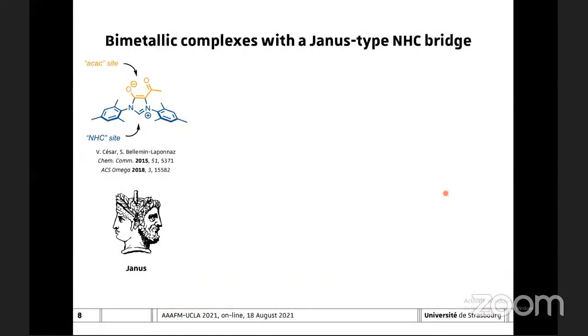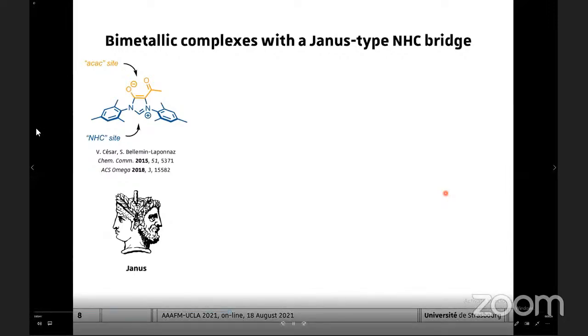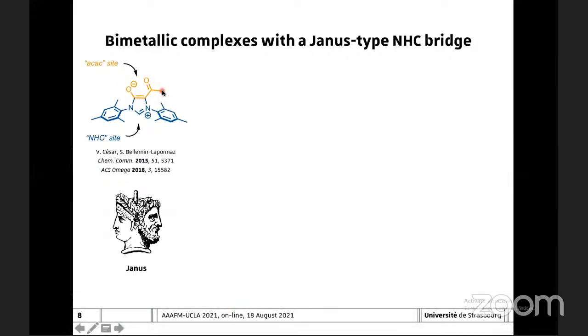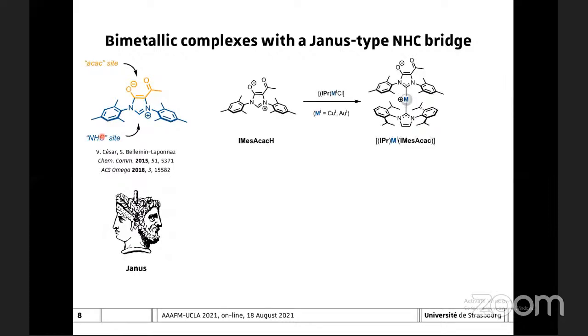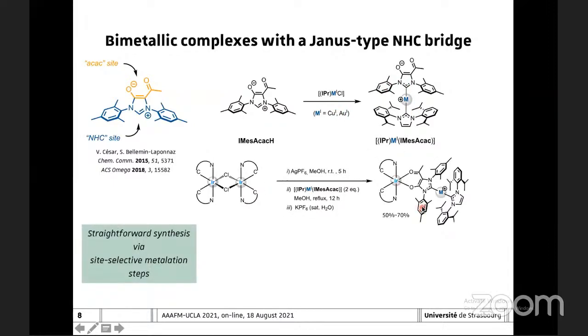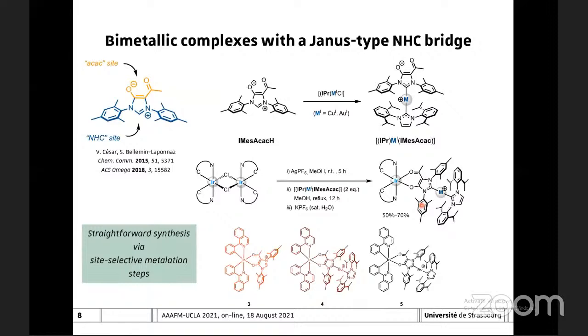So we then came across an interesting ligand. It is a Janus type ligand which possesses two different coordination sites. On one hand, the acetylacetonate site, which is very useful for the preparation of luminescent complexes, and on the other hand, we have a heterocyclic carbene site, which is also very interesting because it's able to form very strong metal-ligand bonds. So we then used these ligands in order to prepare some linear copper and gold bis-carbene complexes, which we use in a subsequent step for the preparation of heterobimetallic complexes in a rather straightforward manner, also by using site-selective steps.